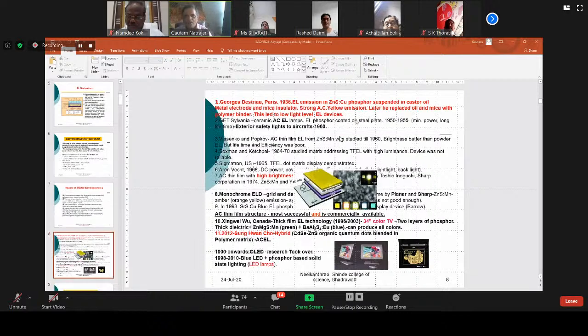Okay, now the history further. 1936, Georges Destriau discovered EL emission in zinc sulfide copper suspended in castor oil. Zinc sulfide copper was suspended in castor oil with electrodes and mica insulator. And when current was passed, you got a yellow emission. Then later, he replaced oil and mica with polymer binder, so means powder form. This led to low light level EL lamps.